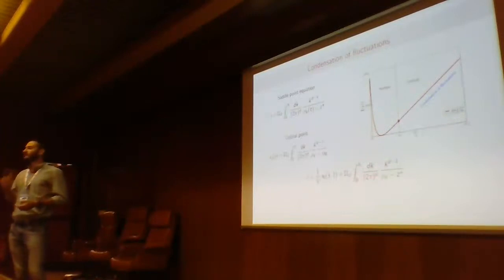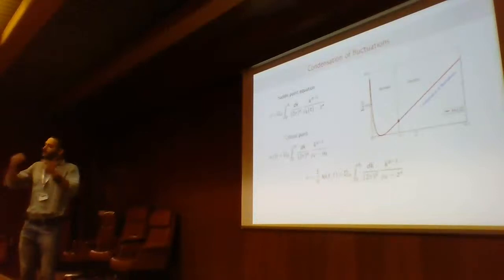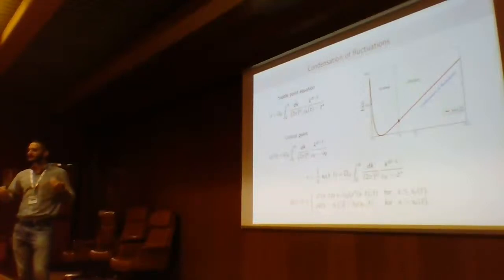This is an integral over the modes, and you isolate the zero mode, which plays an important role here. So this tells us that in that part of the fluctuation, when the observable assumes one of those values, the contribution to the observable from the zero mode is macroscopic with respect to the others. And so we have this form of the rate function, which here follows the equation as before. And here is a straight line. Indeed, S appears linearly. This is why we call it condensation of fluctuation.